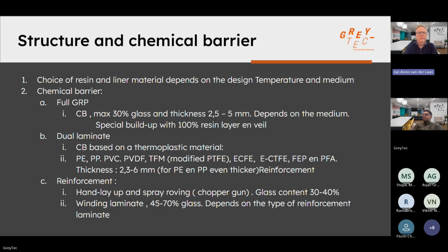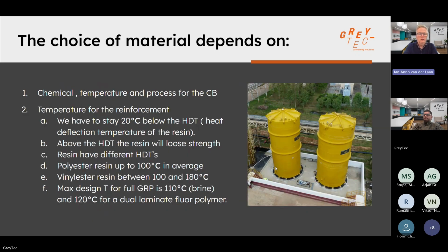How do we select the right material? Well, the material selection depends on the chemicals we want to store and the design temperature. It's always this combination. Resin and thermoplastic suppliers can provide guidance for selecting the correct resin or liner materials. According to the design standard, we must stay at least 20 degrees C below the HDT. The HDT is the heat deflection temperature of the resin. Above this temperature, the resin starts to lose strength.